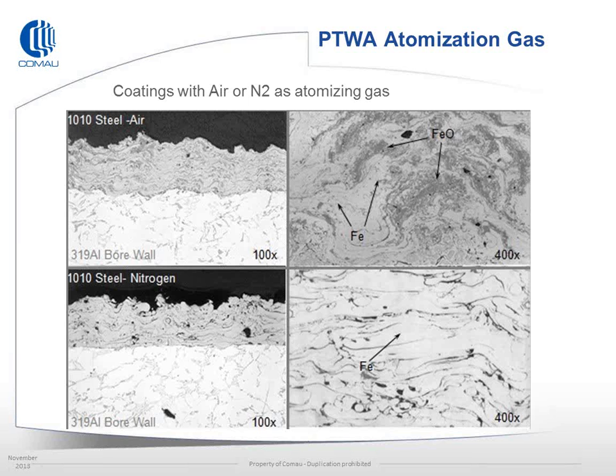In terms of coating characteristics, we have the ability to spray, like I said, with air and nitrogen with PTWA. The advantage of spraying with air is that when we spray a low-cost alloy like 1010, we're able to create a metastable wüstite, or FeO. This provides a lubricious and wear-resistant phase. The FeO fractures across the basal plane, providing a very good lubricious nature to the coating. If we were to spray this with nitrogen, we would create a very fine level of oxide between particle splats.